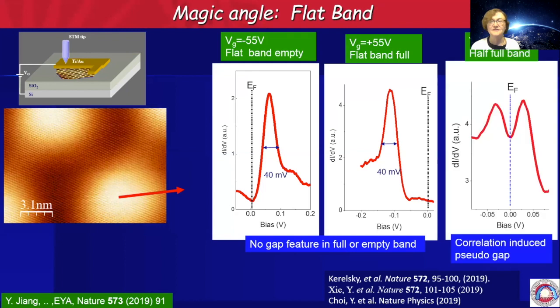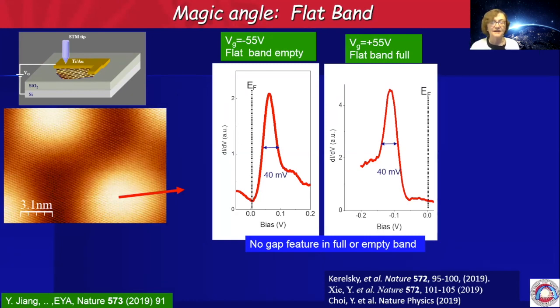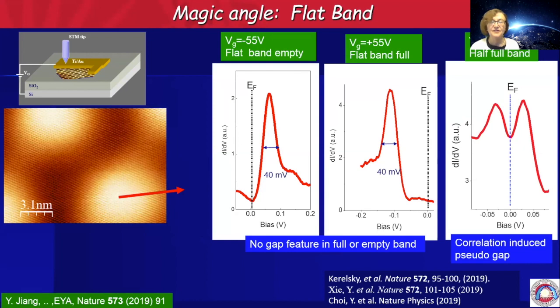And look what happens. We're opening a gap. This is a pseudo gap. This is not a full gap. This experiment is done at 4.5 degrees Kelvin. So this is a classic correlation-induced gap. So we call it a pseudo gap because it's really not a full gap. A full gap would go to zero here. So there are 3 other groups that have seen similar effects from different points of view roughly at the same time.